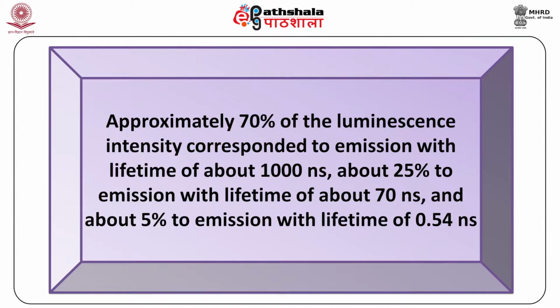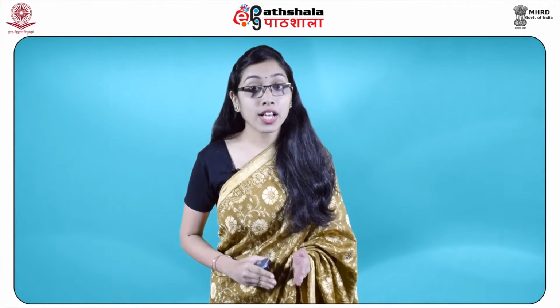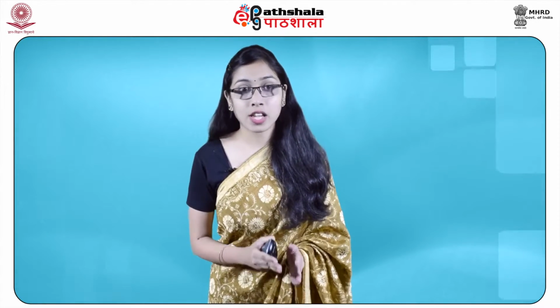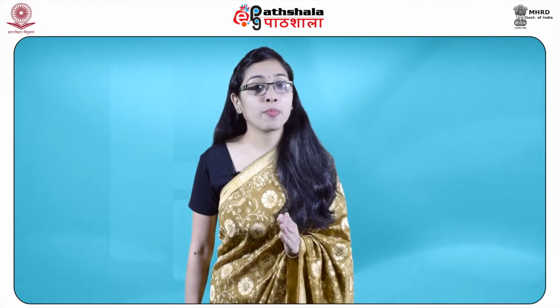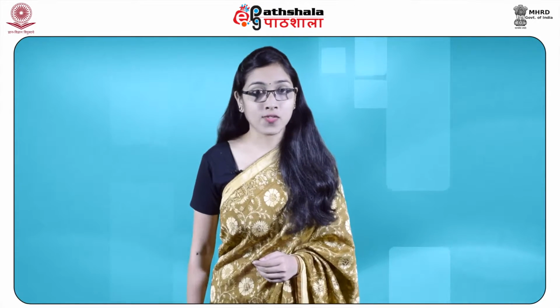Approximately 70% of the luminescence intensity corresponds to emission with a lifetime of about 1000 nanoseconds, about 25% to emission with a lifetime of about 70 nanoseconds, and about 5% to emission with a lifetime of 0.54 nanoseconds. This latter is excitonic emission, and the obtained lifetime is in good agreement with the literature we correlate with. Total luminescence lifetime was measured rather than the lifetime at a particular wavelength or set of wavelengths, because fingerprint luminescence imaging usually involves the total luminescence.